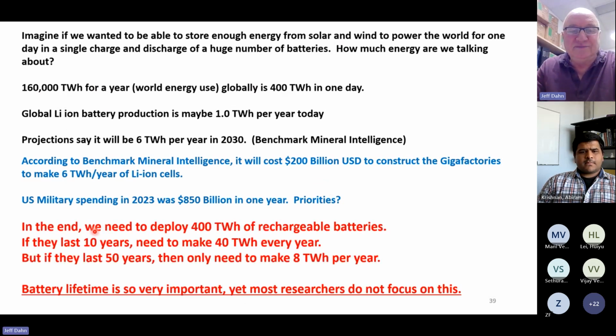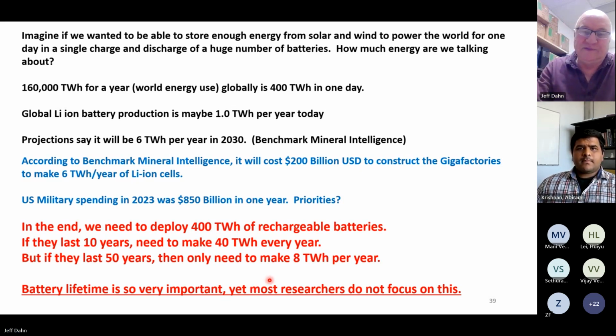You know, in the end, if we're going to eliminate fossil fuels, we need to deploy about 400 terawatt hours of rechargeable batteries. If they last 10 years, you need to make 40 terawatt hours every year to replace the ones that are dying. But if they last 50 years, then you only need to make 8 terawatt hours per year in steady state. 8 terawatt hours per year isn't that scary, because in 2030, we're going to be making around 6 terawatt hours per year. Okay. So battery lifetime is really incredibly important, but most researchers don't focus on it because it's hard. It's really hard to make a long lifetime battery and be sure.